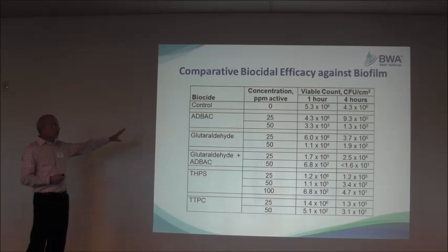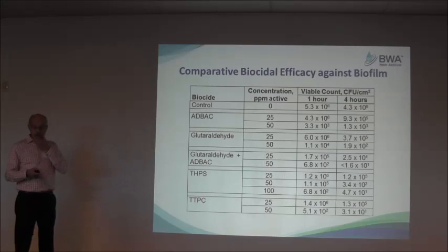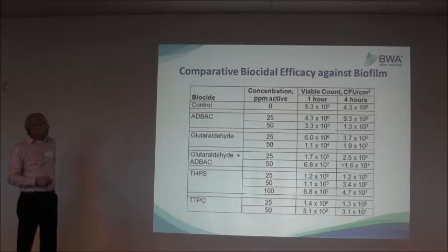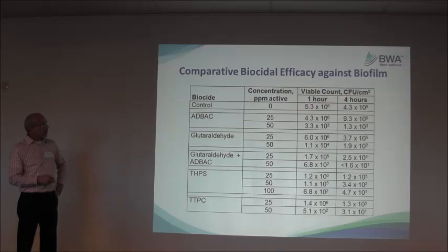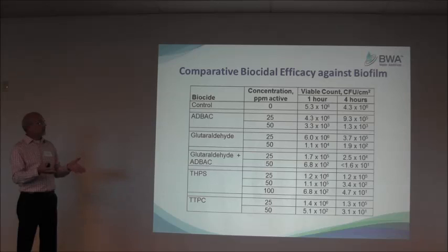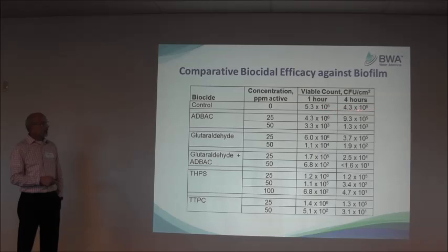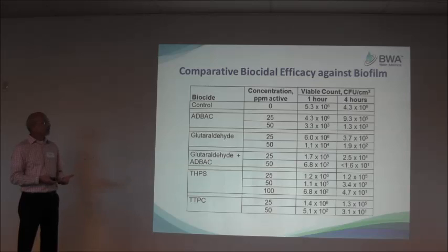There's a lot of data on this slide. In our tests, the control shows a high level of organisms on the surface — about five million per square centimeter. After an hour of exposure to the buffer system, and even after four hours, we still have the same level of viable organisms, confirming the buffer system is not toxic.